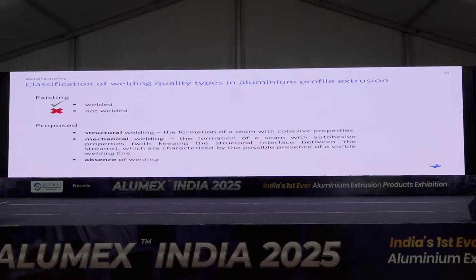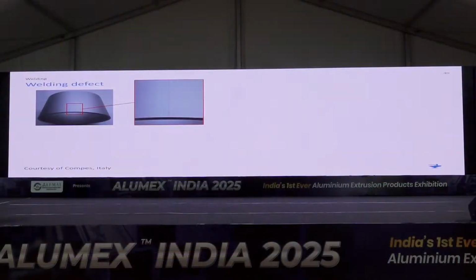And we separated it into three categories. The weld could be structurally welded or mechanically welded. Structural welding quality is okay for automotive and for profiles which require a very high surface quality. Mechanical welding is okay only in the case when this surface will not be visible to the eye. And then there is the absence of welding, basically the not-welded stage, which is not that easy sometimes to achieve, but it happens.